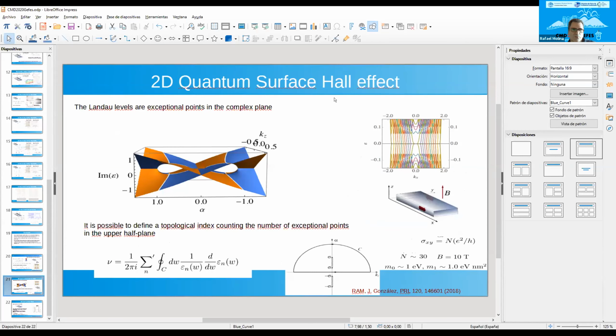In the case of the 2D quantum surface Hall effect, we can come up with a topological index that counts the number of states. We do this by changing to the complex plane, because the Landau states from the surface can be transformed into exceptional points, and then we can use tools from complex calculus to find this formula for this topological index. And here we expect a nice quantization of the conductance up to very large numbers of n.